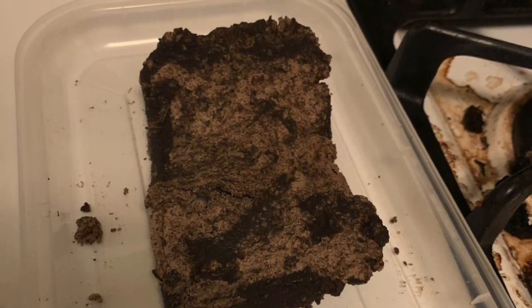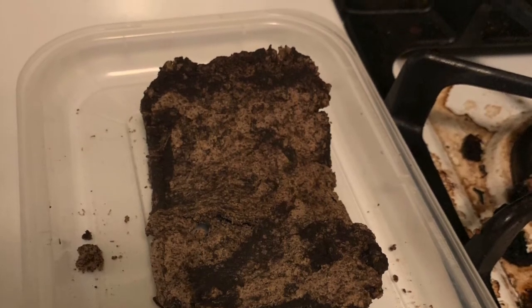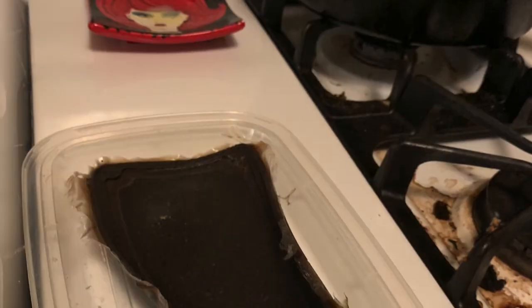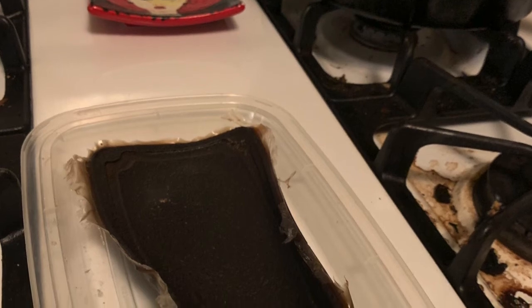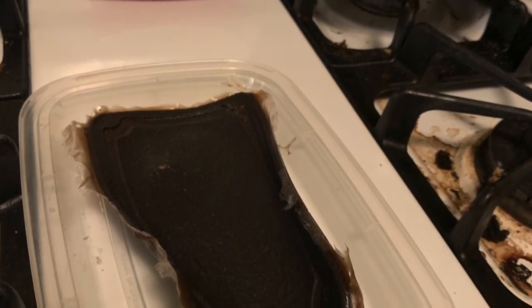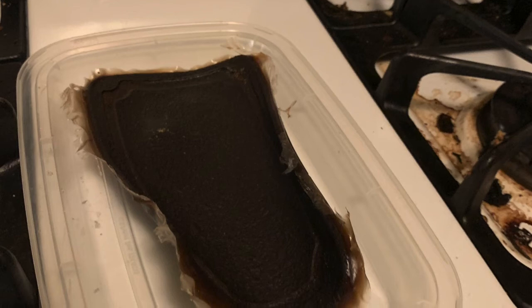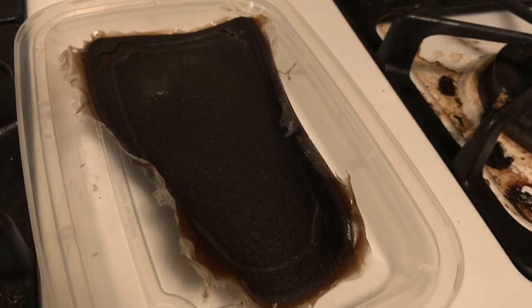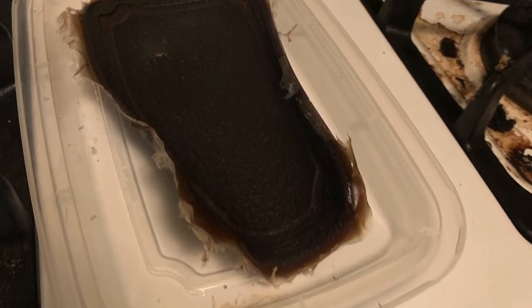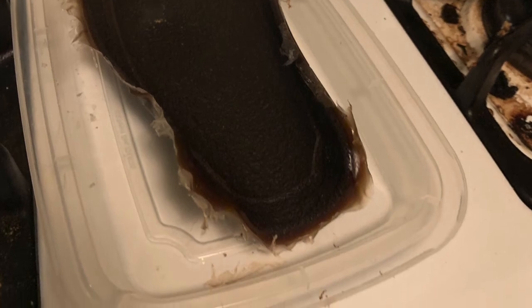The most successful samples from these experiments were combinations of gelatin and avocado pits or acorn flour. The blend of agar-agar and acorn flour proved somewhat successful as the material shrank and curled in the mold. Other blends cracked as they dried.